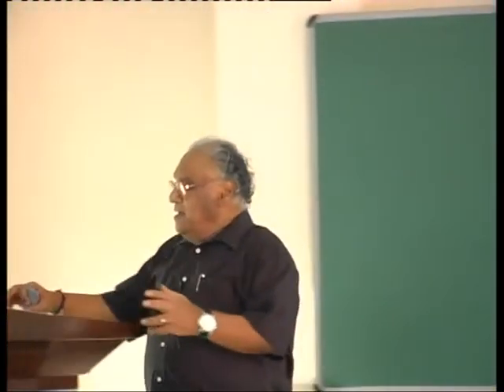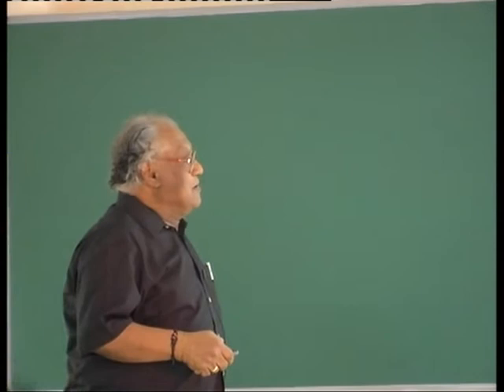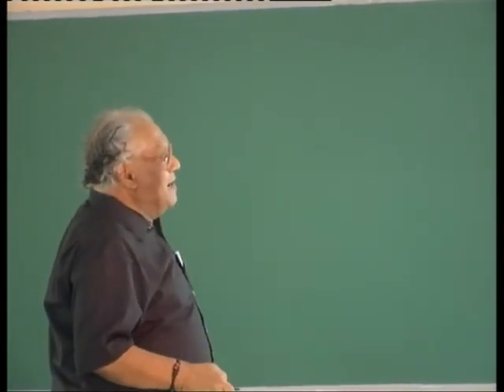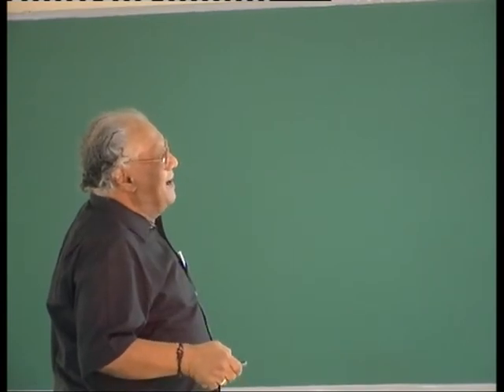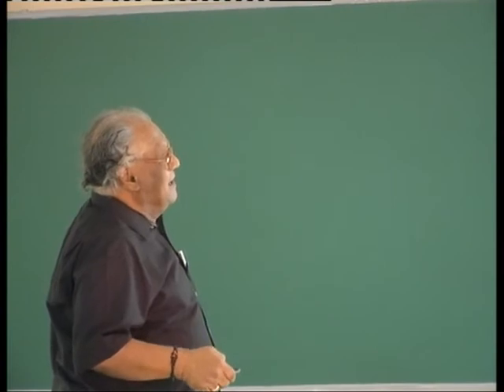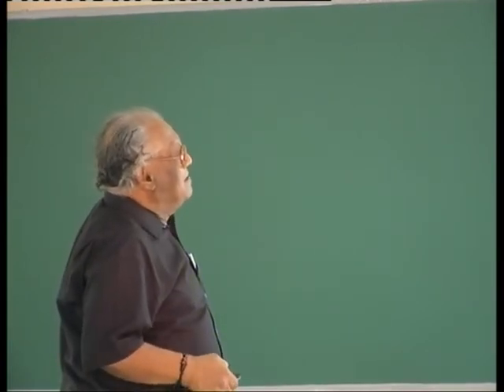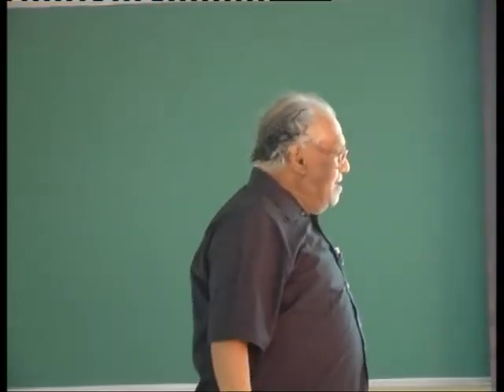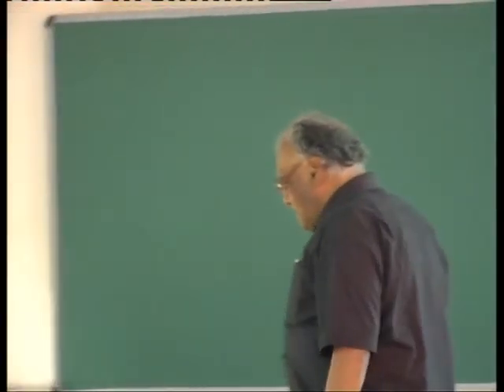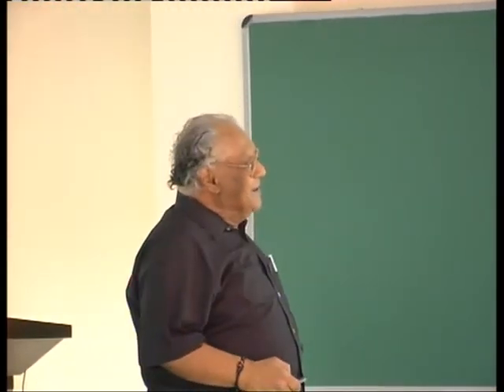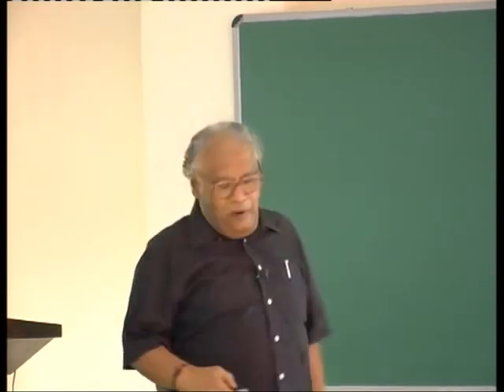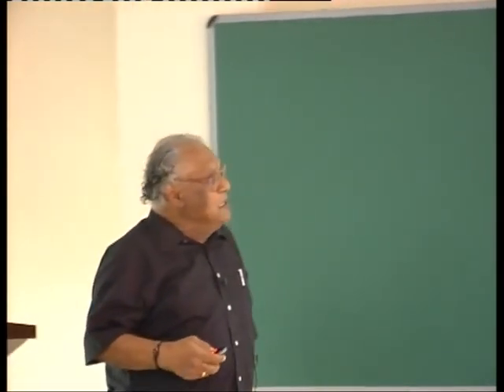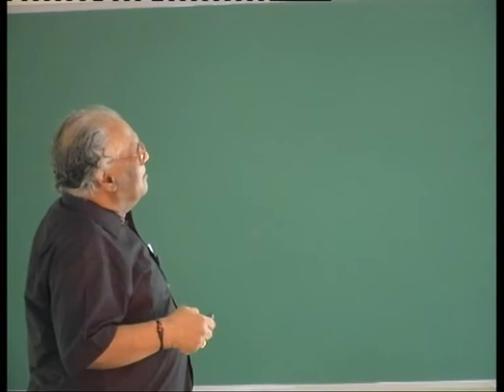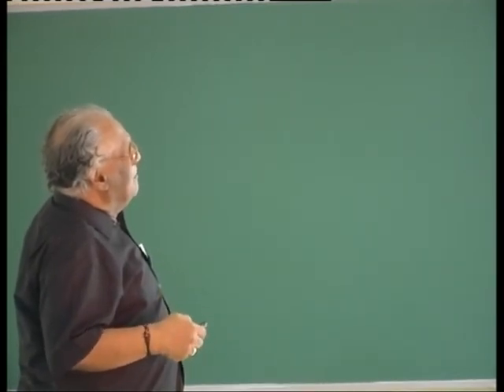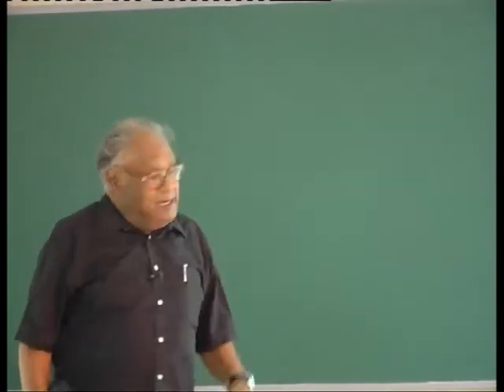Well, I think there may be a better curve. Yeah, here it is. You can see the magnetocapacitance is very small. You can get 1 or 2% of magnetocapacitance in composites of this kind made in the lab. Well, of course, there is a paper by Ramesh. I never saw the curve was parallel to the x-axis. He said there was 0.1%, but I couldn't see the change in anything. It was so small, the figure didn't show it. On a similar material, we have 1.5% with particles. However, if we make nanotubes or nanowires, we can get up to 5% in composites of two nanoparticles, core-shell type of nanotubes or nanowires of this kind. So barium titanate, cobalt ferrite type of composites, where one is ferroelectric and another is magnetic.